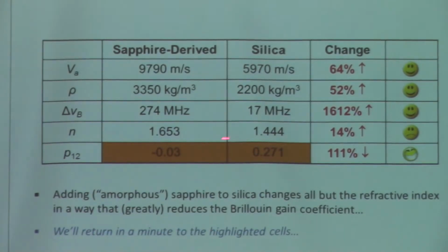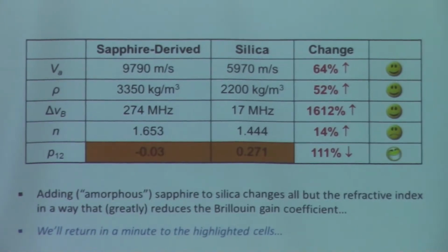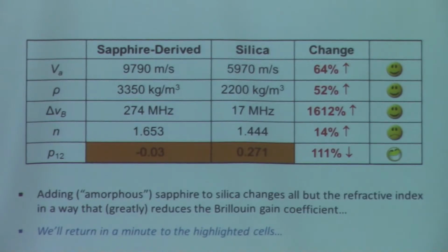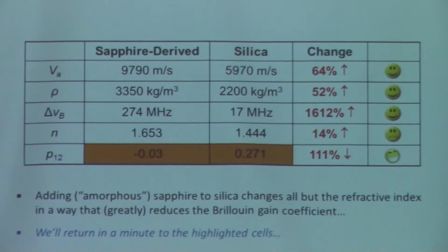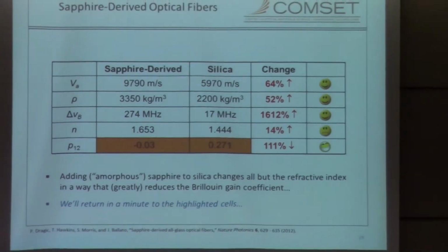This is fascinating too, because again, why is it so good? It isn't just that these numbers fall into these equations. There's got to be more to it than this. And what we hadn't realized, because nobody had ever studied this before, because you couldn't make these glasses before, because you were wed to this manufacturing process, is that when it comes to this acousto-optic squishiness, silica has a positive value. Depending on how you want to think about this, as a light wave moves through, the effect on the sound is opposite than in the case of alumina.